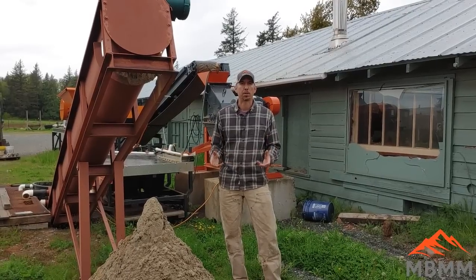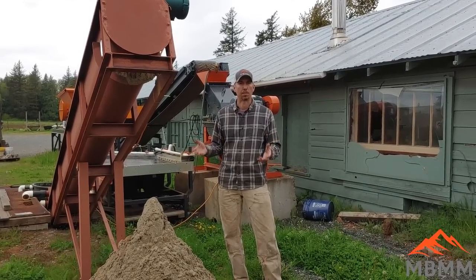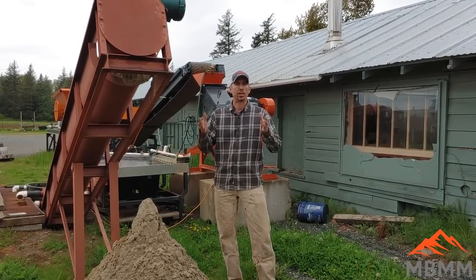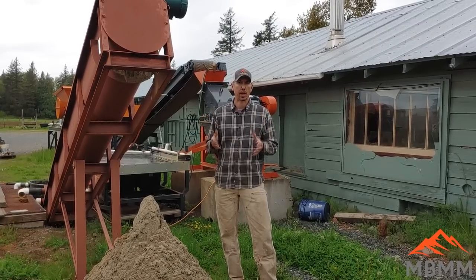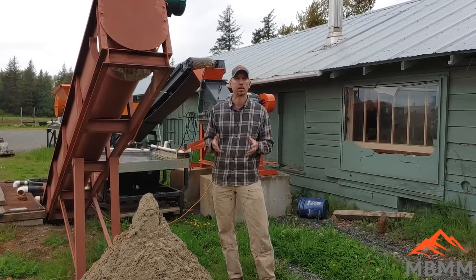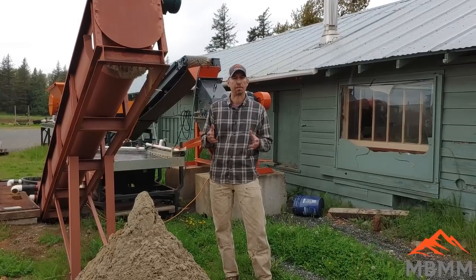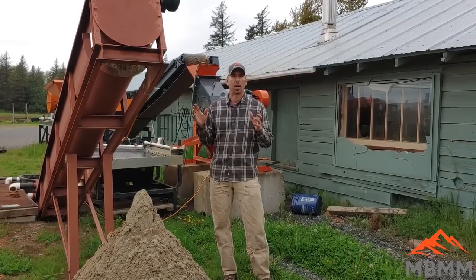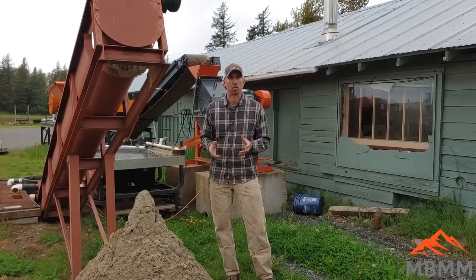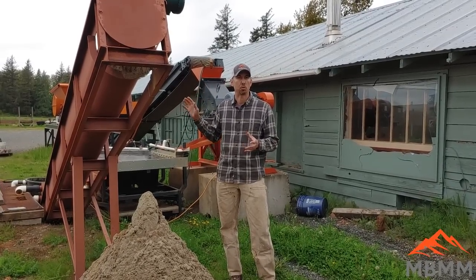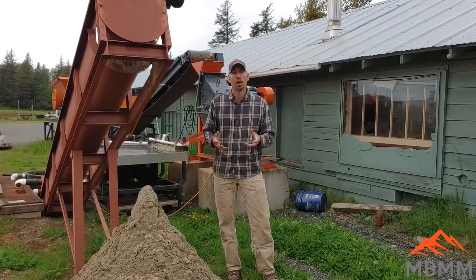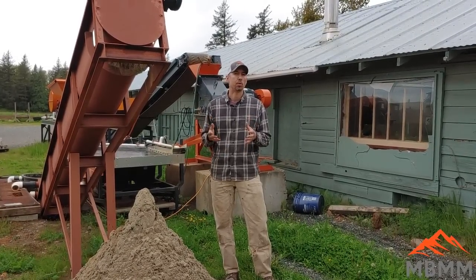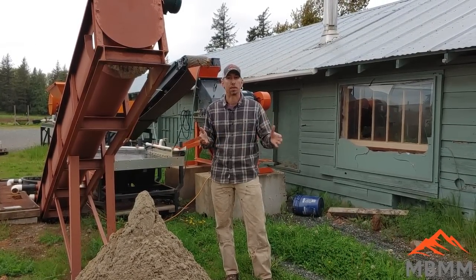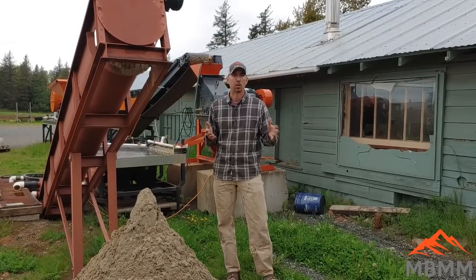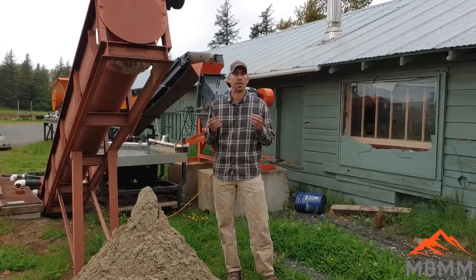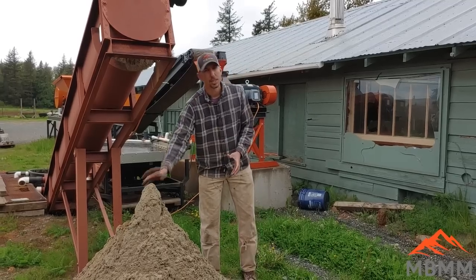One of the really important parts to understand as an operator or a bulk sampler of a gold claim is your goal is not to initially recover as much gold as you can. Your goal is to get the information you need to go for the next step for investing in machinery. And so that's why we did our grind size analysis. With the hammer mill and the system as it is, we're recovering about 75% of the gold. But we found out that if you can grind to 100 mesh minus, you can recover somewhere in the 90% plus gold recovery. And so this material here out of the spiral classifier, this is still a resource.